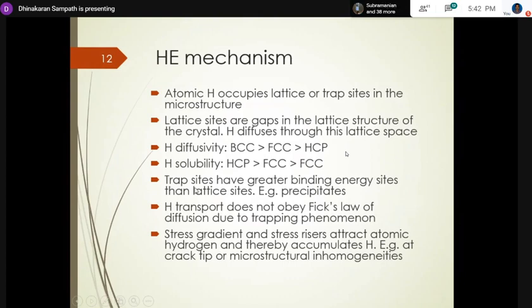So traps have greater binding energy than lattice sites. For example, some second phase particles will hold more hydrogen. That means it will accumulate more hydrogen in that location, and we'll see some mechanisms which tend to weaken the location because of the trap sites, and also they are sometimes beneficial. So that's the trick. And because of this trapping phenomenon, hydrogen transport doesn't follow Fick's law of diffusion, so we can't use that. There are many models, starting from the Oriani model, that account for trapping as well, to understand how the hydrogen transports.